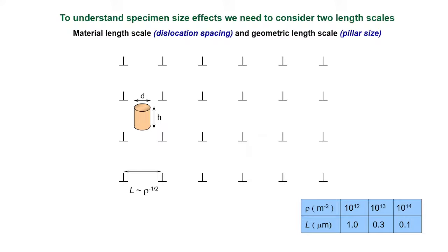So you have 2 length scales. One is the spacing between the dislocations, and one is the size of the pillar, right? So in one case, if your pillar is so small that it entirely falls between these other dislocations, there'll be no dislocations inside the pillar. Or you could go to very large pillars, in which case you have lots and lots of dislocations, right? And on average, you would behave like a bulk. Here you would behave like ideal single crystals, like Brenner's classic paper.